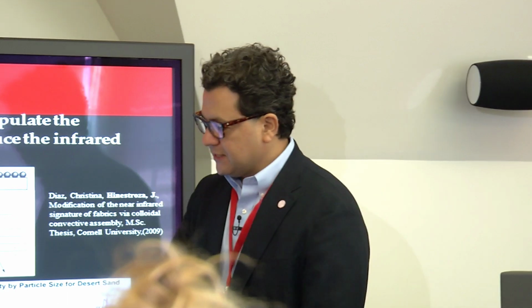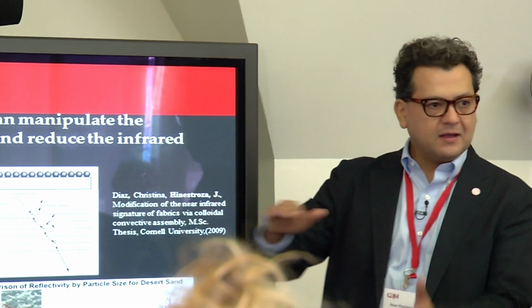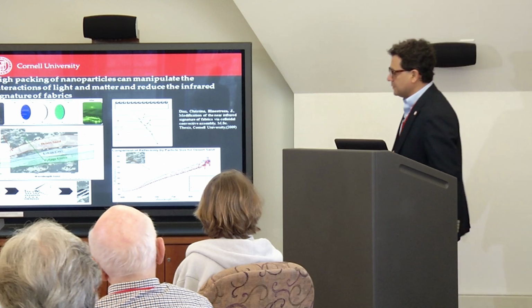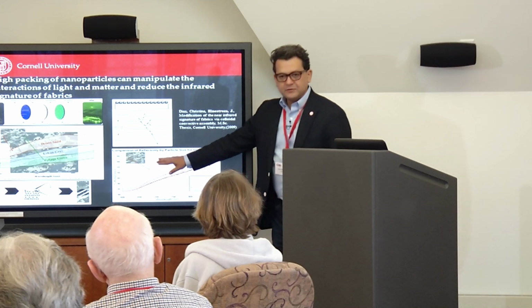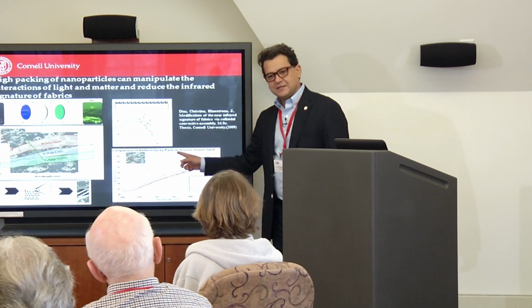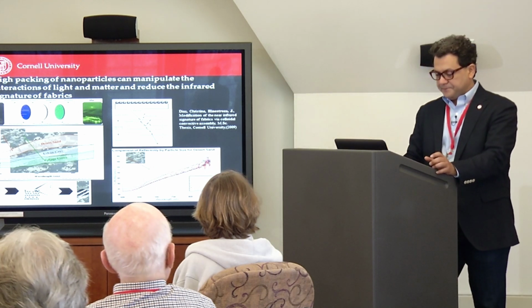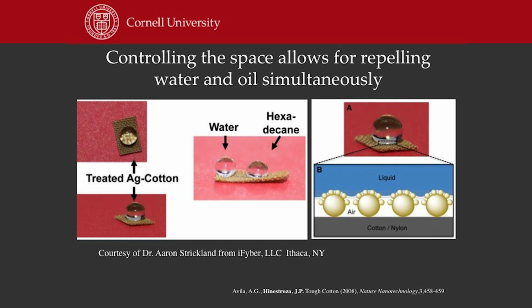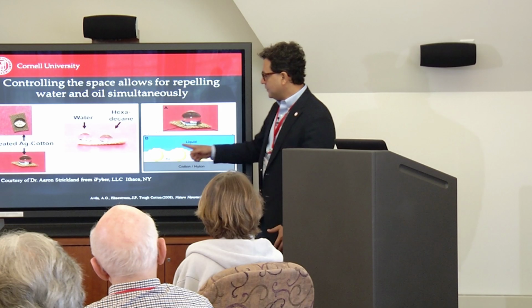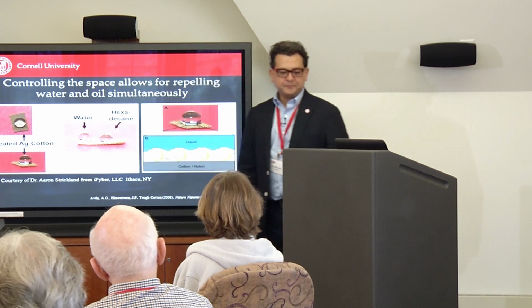And the camouflage that we saw this morning has 3 colors. So we have ways to create optical filters by controlling the spacing of the particles and how we place them on top of each other. So my student was able to take these colors out of the range of visibility. So this is the range of visibility, just by using particles. And the particles were so close to each other that you can make little pockets of air between particles that prevent these materials from being wet. No liquids, no oils can go through. So nothing gets wet. You put oil, it bounces back, water, bounces back.